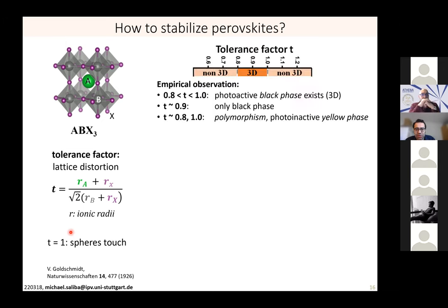And empirically, it was discovered that a tolerance factor between 0.8 and 1.0 gives a black phase, or an alpha phase, which is photoactive. And these are the typical 3D materials people look at. If we use this equation and use these as boundary conditions, a tolerance factor between 0.8 and 1, it means that the cation which can fit here has to be about 2.7 angstrom, around about. So there are not many materials which can fit here without distorting the overall lattice structure.